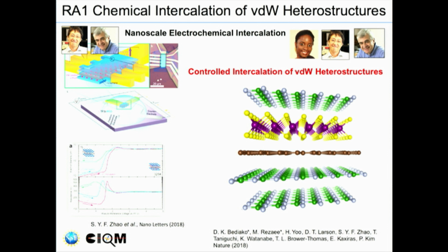And so if you put it in the right stuff, the molecules go in between the carbon layers, and it's called intercalation. And you can expand the material a lot, by tens of percent, and change the properties a lot. And that was a very active area. And what they're doing now is instead to start with just a few layers of graphene and then to intercalate it by pulling the material in with an applied electric field. And so it's electrically controlled intercalation. And the idea, again, is to make a new type of layered material that didn't previously exist and do that by design.